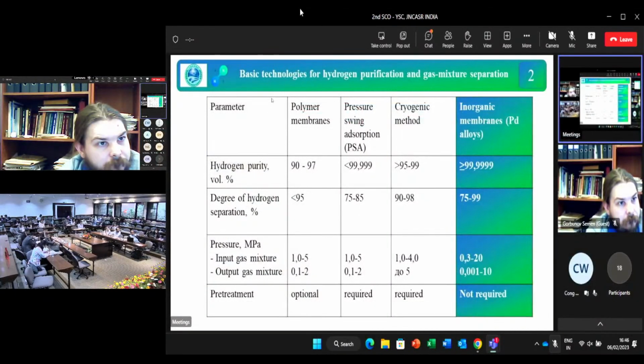The principal requirements for membrane palladium-based alloys include high hydrogen permeability, low dilatation while saturating with hydrogen, stability in corrosive gas media, and high plasticity and strength during operation in the temperature range of 300-600 Celsius. The reliability and effectiveness of the membrane operation in various gas media are also related to the catalytic activity of a membrane alloy in a given medium, and the dynamics of hydrogen permeability and mechanical properties, which are caused by structural and surface changes occurring during operation of a membrane.